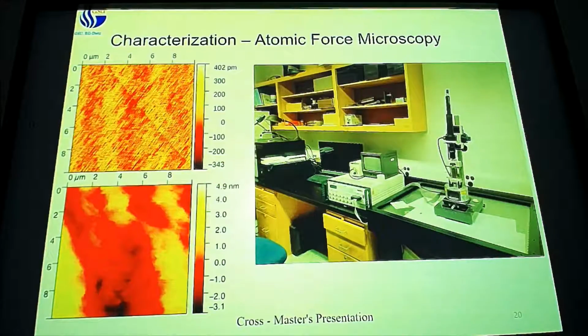So this one is about 1,100 nanometers of our gallium nitride grown on top of a gallium nitride substrate, which we purchased. This one is about 2,500 nanometers of gallium nitride that we grew, 1,100 and 1,400 at separate times. Just relax. It should be totally relaxed by this point, yes.